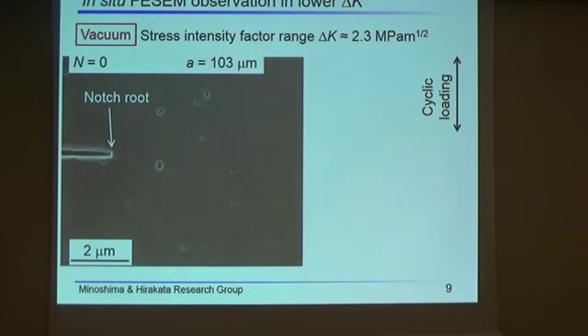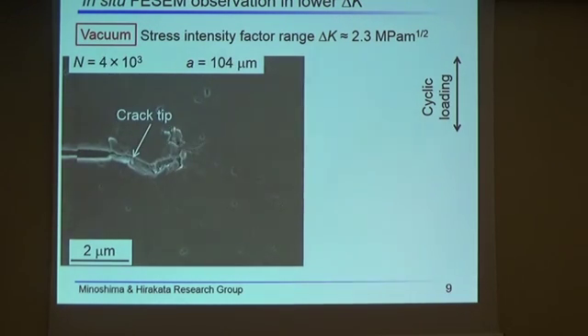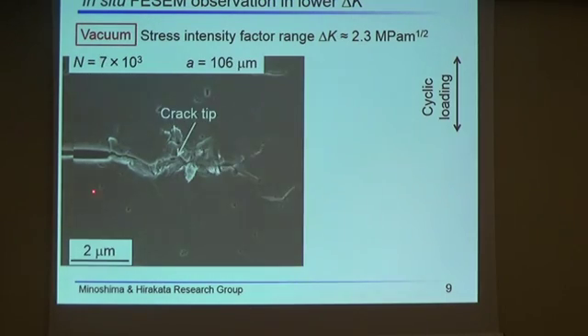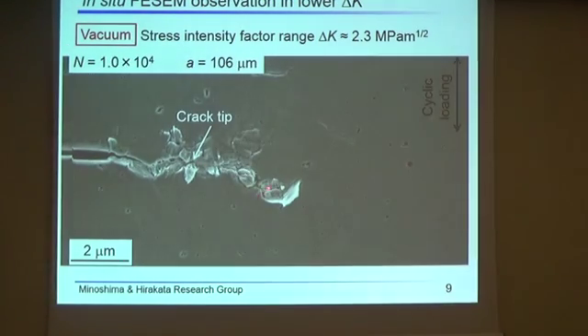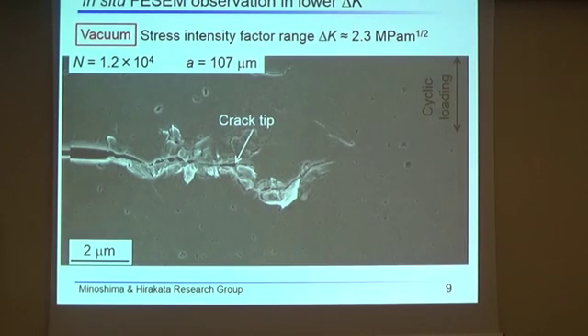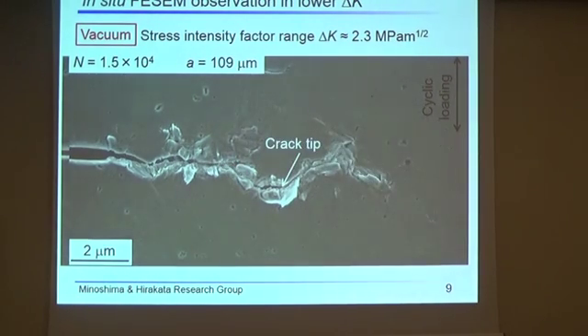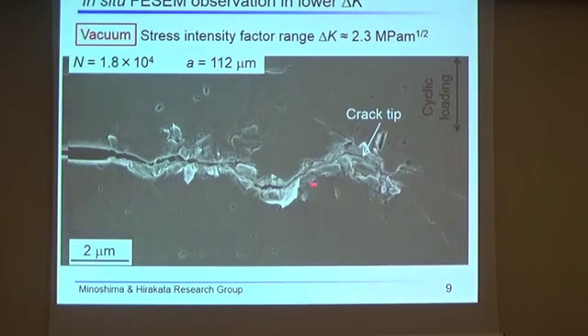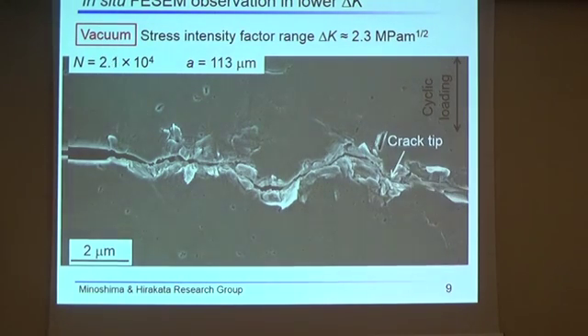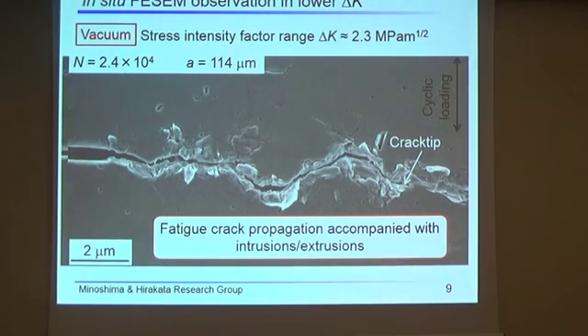maximum stress. By applying cyclic load, the fatigue crack started to propagate, and fatigue damage, or intrusions and extrusions, formed ahead of the crack tip. And then the fatigue crack propagated through these intrusions and extrusions. So this fatigue crack propagation behavior is similar to that in air.